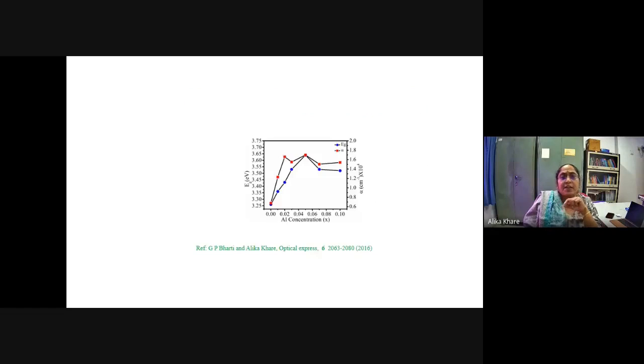Another example is the tuning of the band gap, the thin film with the tunable band gap. Here I am showing the example of the ZnO film with aluminum impurity infused into it. The idea was to increase the band gap of ZnO further into the ultraviolet direction. The blue dot indicates the band gap of the AZO, aluminum infused ZnO.